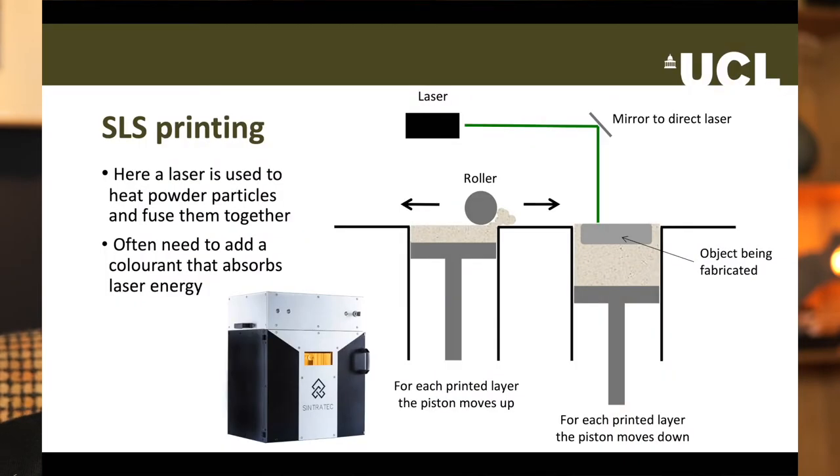The other type of laser printing we use is known as laser sintering. Here, a laser is used to heat particles up and cause them to fuse together, as shown in the schematic on the screen. Much like the powder bed printer mentioned earlier, a layer of powder particles is spread out, but rather than using an inkjet print head to spray a glue, a laser beam is moved over the particles in a raster pattern. The energy in the laser heats the particles up, causing adjacent particles to fuse together. Again, the laser creates the first layer of the object before a second layer of powder is spread out and the process repeats, exactly like the powder bed printing process discussed earlier.